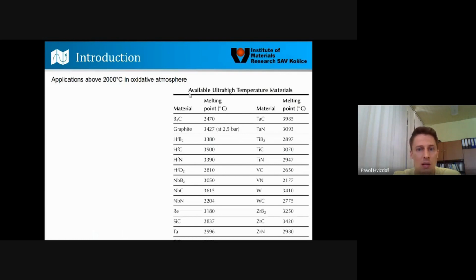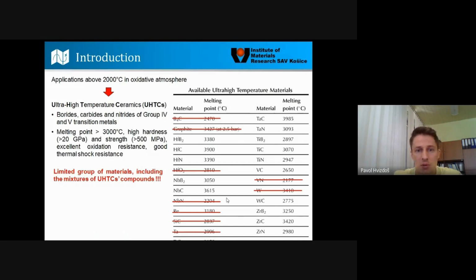Of course, if we check the available so-called ultra-high temperature ceramic materials, we can have a list. But unfortunately, not all of them are good for that extreme environment. This is because many of them can burn. So, for example, graphite is the material which possesses the highest melting temperature, but it burns over 900 centigrades. Also, in some cases, there is some problems with the heat transfer. So the materials we really look for as an ultra-high temperature ceramic material should possess good thermal conductivity and relatively low thermal expansion. So this means, for example, oxides immediately pulled out from this list. And basically what remains is about 20 materials.